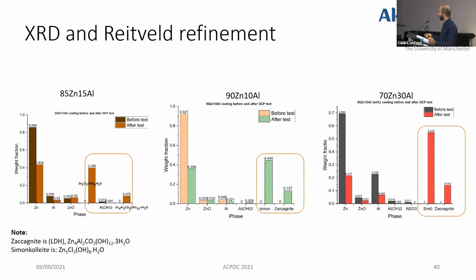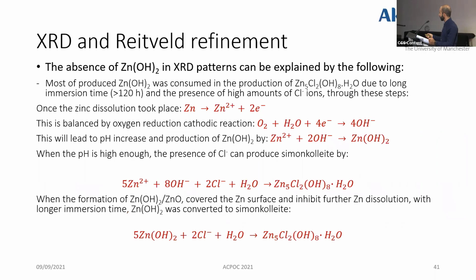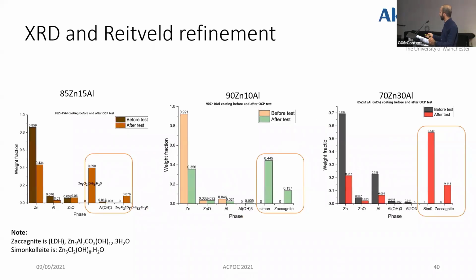these coatings. So there is no comparison between each coating because the software only calculates. You cannot compare this with that one in the numbers. So it's just for a specific XRD pattern. But you can see there is a high amount of these two corrosion products, simonkolleite and zaccagnite, in these zinc aluminum coatings. If we can go back here, there is no appearance of zinc hydroxide in the XRD pattern, which is supposed to be the first corrosion product in zinc dissolution.